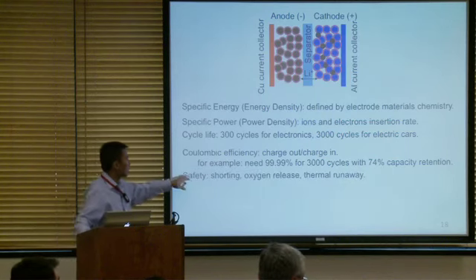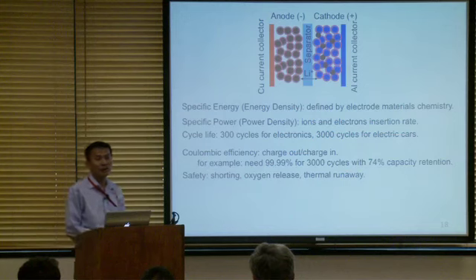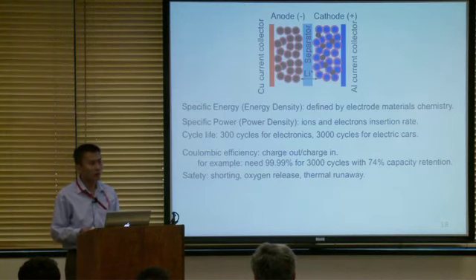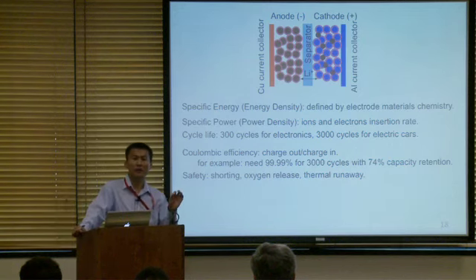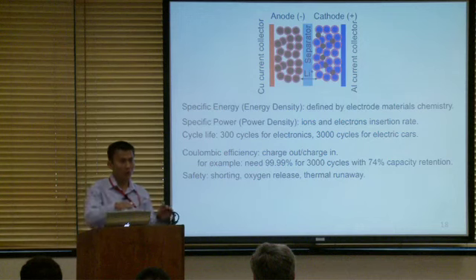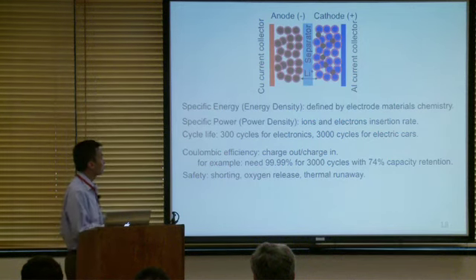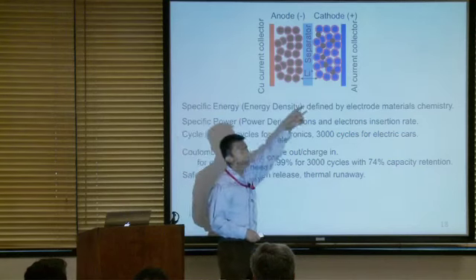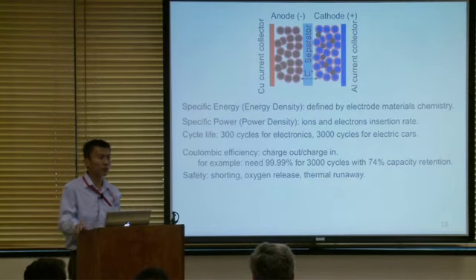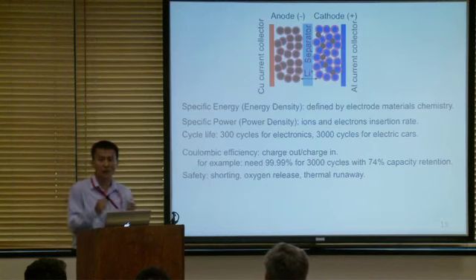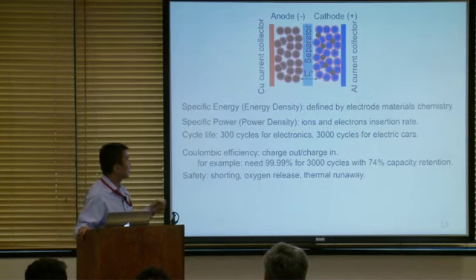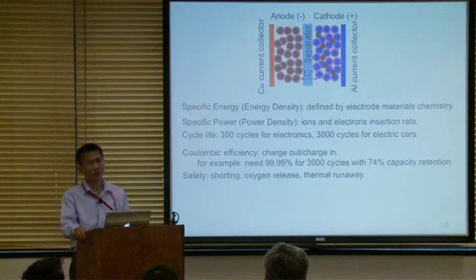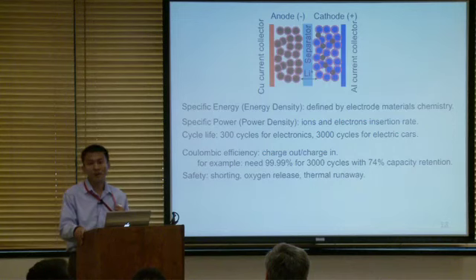So let me mention a little bit more about safety. How does the safety concern arise, how does a battery explosion happen? One reason is the lithium dendrite formation. Once you go to low voltage, you deposit lithium metal out, and it's going to grow from the positive to the negative side, and then short your batteries. Once you have shorting, that generates heat, and heats up the batteries. Now lithium cobalt oxide can start to release oxygen, which comes back to oxidize the electrolyte. So it's going to explode.